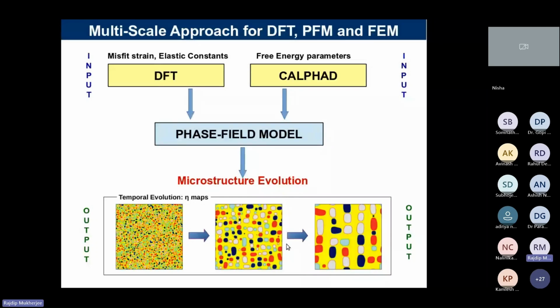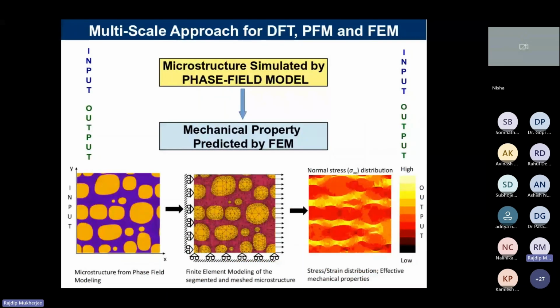So once we have the output of the microstructure, how it evolves, we also need to know the corresponding mechanical property of this material, right? And these precipitates are in the nanometer to micrometer region, so in the mesoscale regime, right? So next, once we simulate the microstructure using a phase field model, the mechanical property can be predicted using a finite element model. And this will be demonstrated in the second demonstration today in the afternoon session. In this figure you can see the microstructure from phase field modeling. Then there is the finite element modeling, segmented and meshed microstructure. And finally, we can get the stress strain distribution. We can get the effective mechanical properties from these stress strain distributions, right?